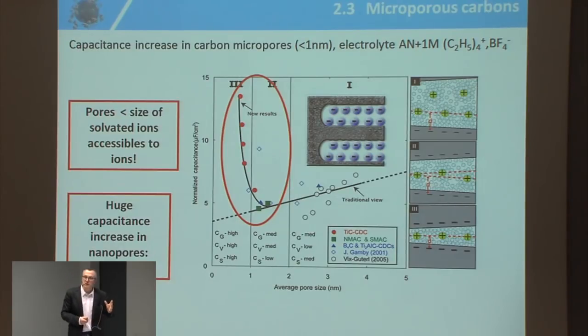And people thought that below 1 nanometer, there was no way for ions to go inside pores, because solvated ions were bigger than 1 nanometer. However, when we did our carbons using a very specific technique, we have shown that first, pores smaller than the size of solvated ions were accessible to the ions. And second, there was a huge capacitance increase in these nanopores.